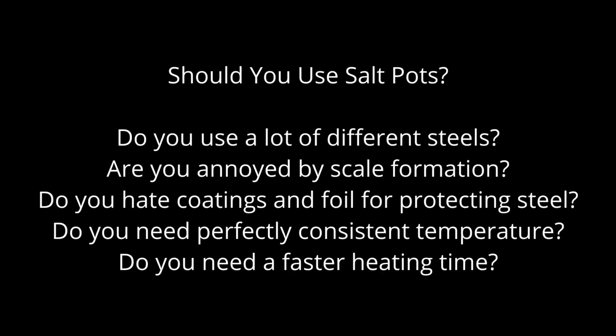So after all this, do I recommend salt pots for austenitizing? With the way that I work, I don't really think salt pots are for me. The main reason being that I heat treat a wide range of steels with a wide range of austenitizing temperatures. So if you only use a narrow range of steels with a narrow range of austenitizing temperatures, you may benefit from salt pots that you can work a little more quickly and heat treat a lot of small pieces rapidly.